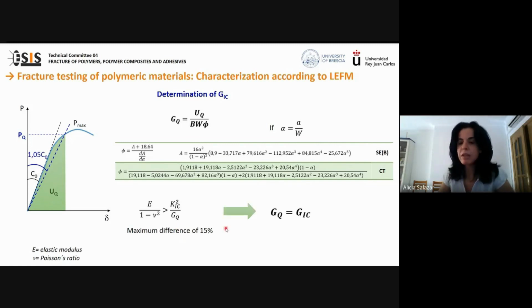If this is fulfilled, then GQ is equal to the critical energy release rate. Otherwise, the results should be inspected for possible errors. The Young's modulus and the Poisson's ratio are obtained from mechanical tests such as tensile tests carried out at the very same experimental conditions as those used for the fracture characterization. Typical values of G1C for brittle polymers are in the range between 17 and 200 joules per square meter.